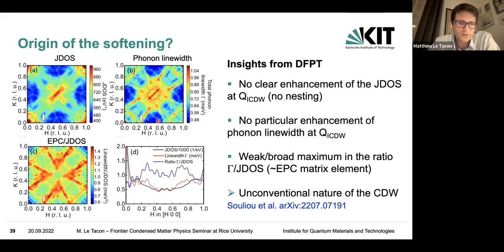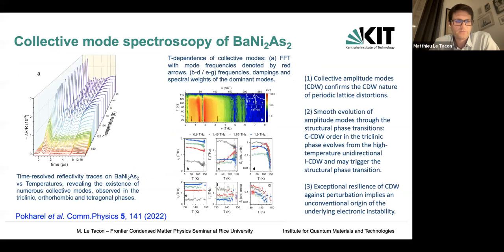And you see that there's no clear maximum here, and you can divide the electron-phonon coupling, the width, by the joint density of states. What you find here is some kind of broadish maximum of this ratio around the Q of the instability, but nothing that looks like a diverging feature. So there's no particular enhancement of the electron-phonon coupling at that Q. It is pretty mild, and that indicates a fairly unconventional nature of the charge density wave.